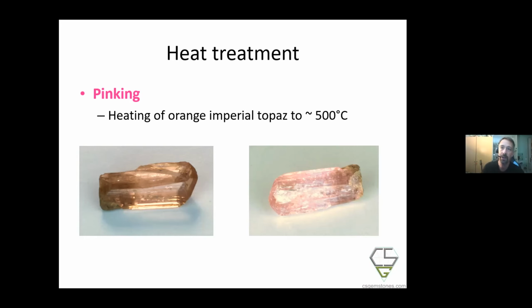We did FTIR spectroscopy, we did Raman spectroscopy. You see a change in the hydroxide content. However, in nature, you have such a huge distribution of possible abundances of peaks, so that it's not possible to say, if you just get one specimen, that it has been heated or it had not been heated. You might have some indications, but again, it's not really possible to determine this pinking here.